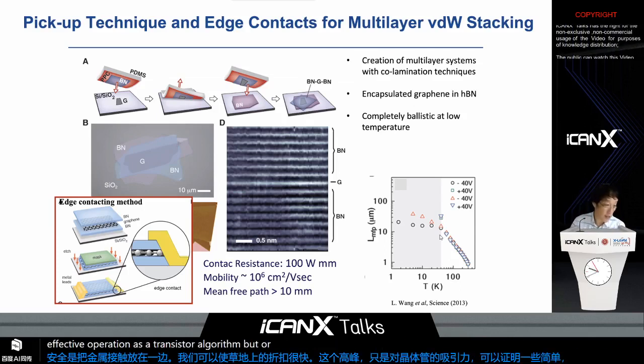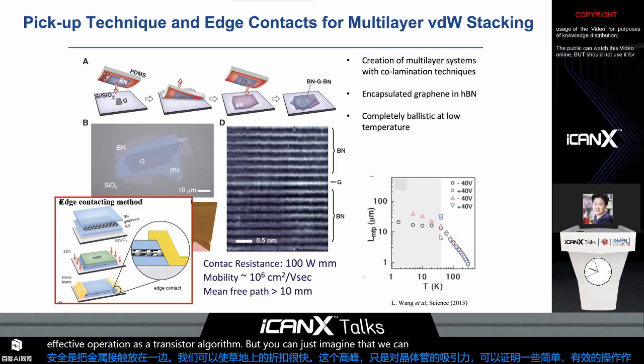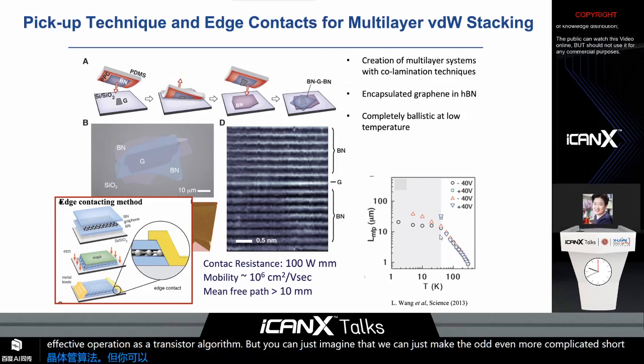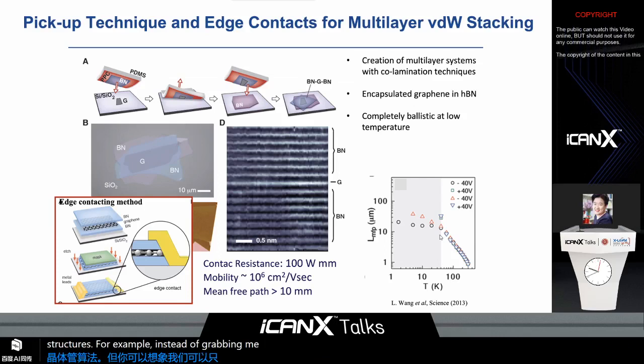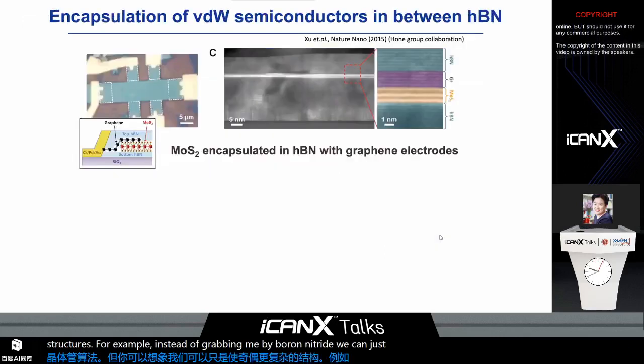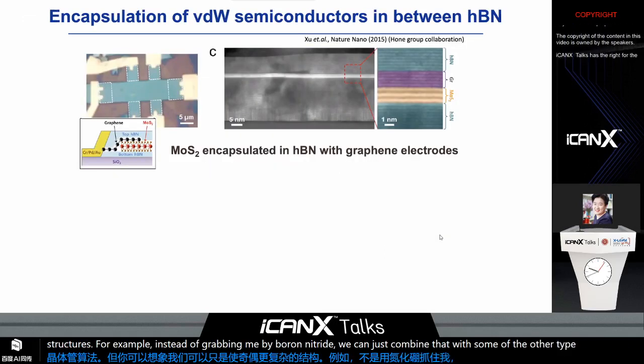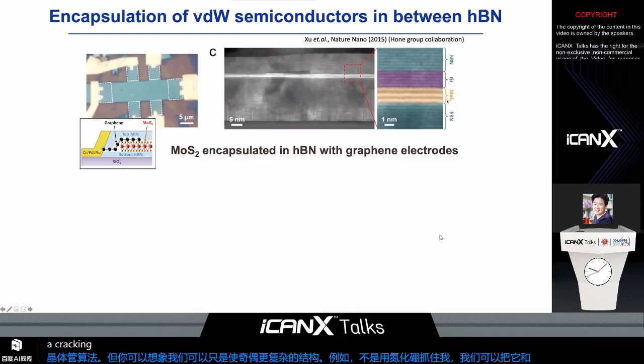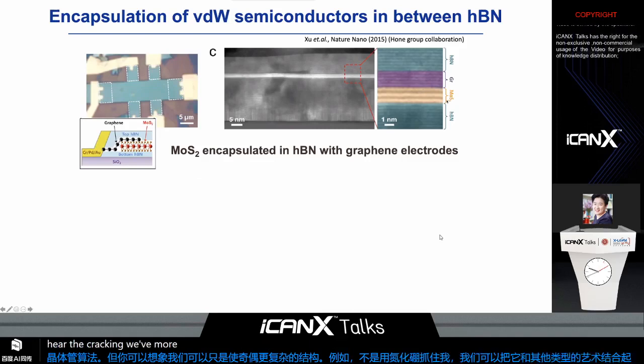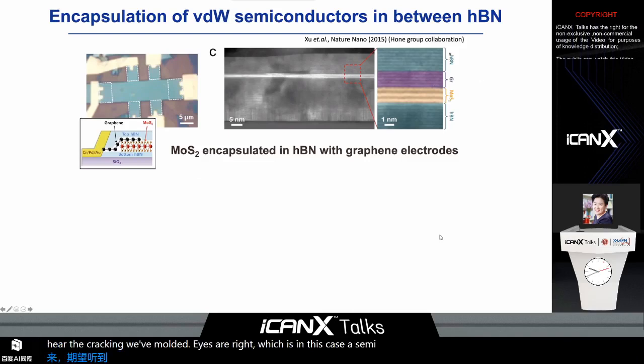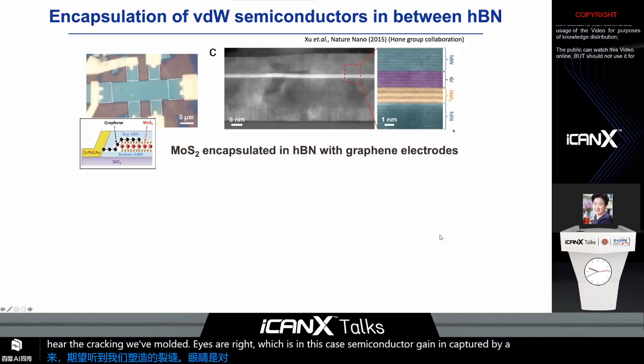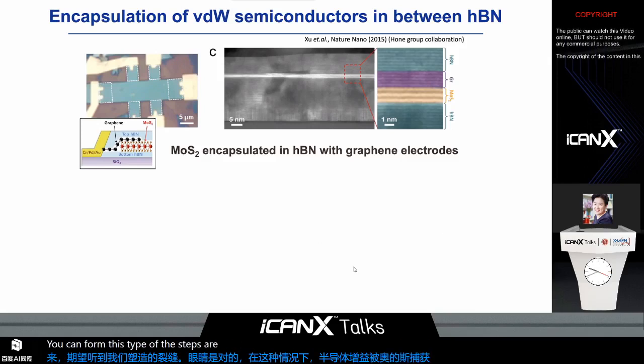But you can just imagine that we can make slightly more complicated structures out of it. For example, instead of graphene with the boron nitride, we can combine that with some other type of atomic stacks. Here, the graphene with the moly disulfide, which in this case is a semiconductor, again encapsulated by this hBN, that's again an insulator. You can form this type of stack with various different kinds of properties.